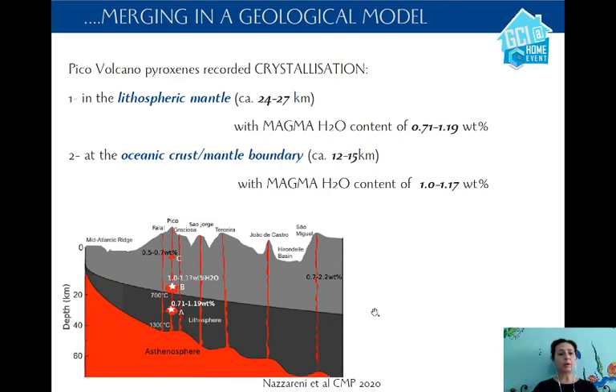The magma water content recorded by pyroxene from the lithosphere to the crust-mantle boundary is more or less the same, because it varies at the lithospheric depth from 0.7 to 1.2 weight%, and at the crust-mantle boundary from 1 to 1.2 weight%. So we can say that the water content in magma from the lithosphere where pyroxene started crystallization up to the oceanic crust-mantle boundary did not change significantly, and was on average around 1 weight%.